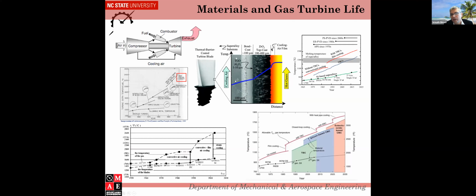So you have a lot more things going on the surface of the blade, thanks to material scientists, because they have invented very high temperature coatings that can protect the metal so that the metal doesn't burn off. And when the burn off does occur, it affects only the coating. So when you take the part out, you basically coat the part again and then reuse the part without losing the part.